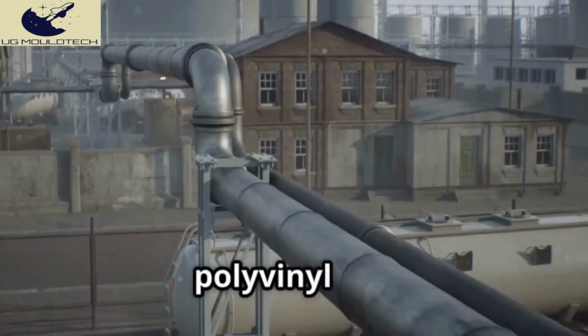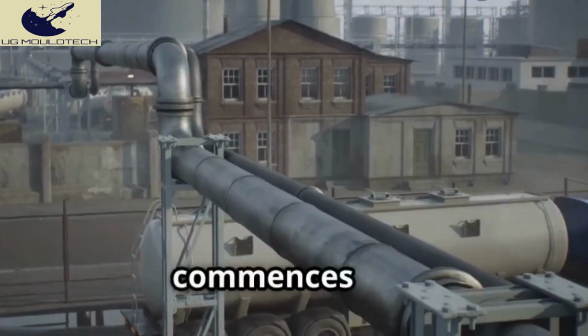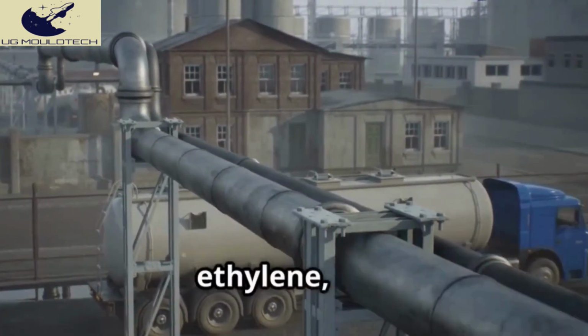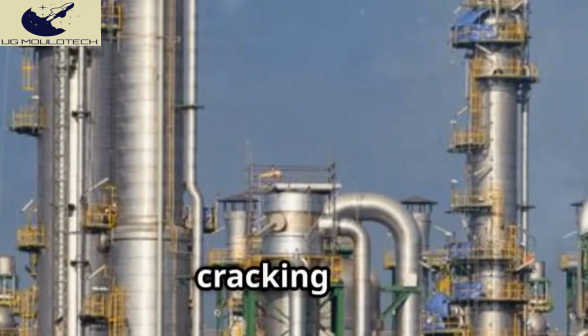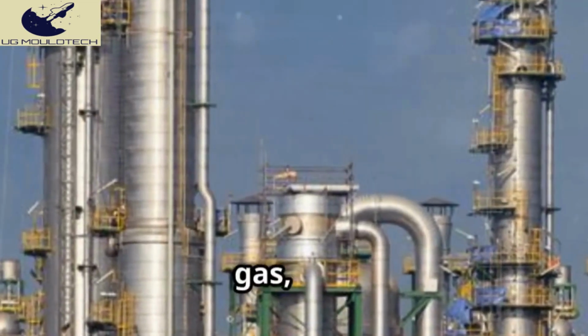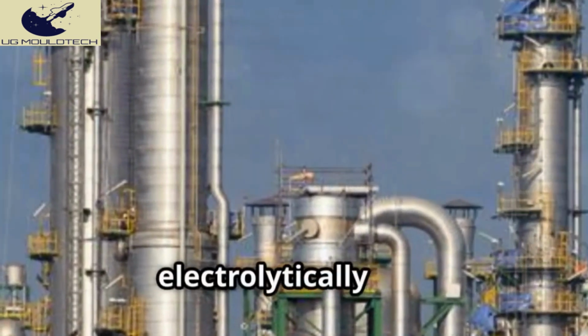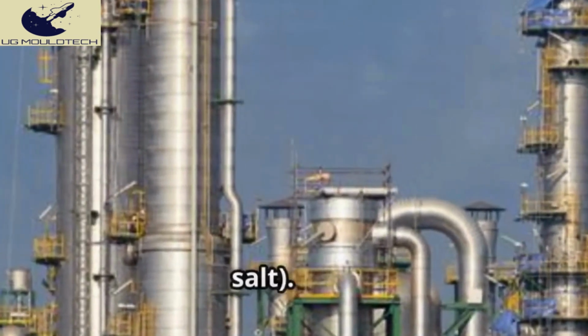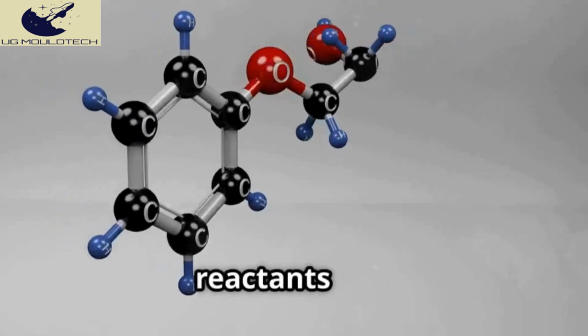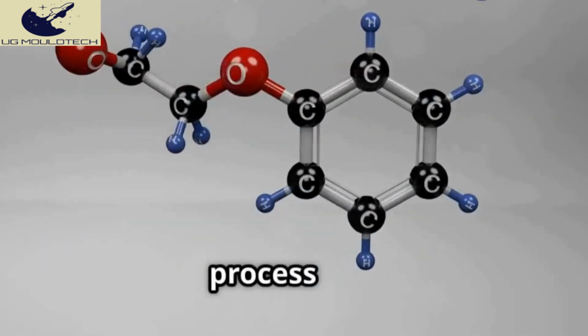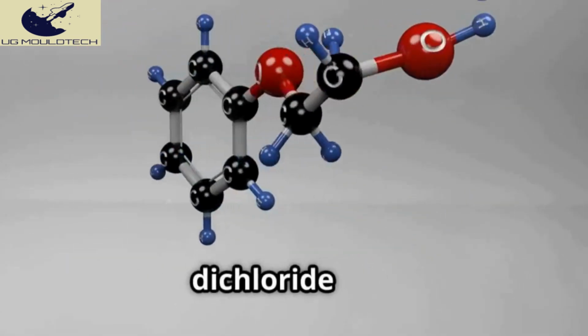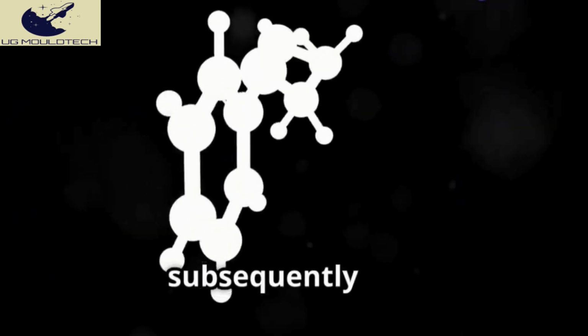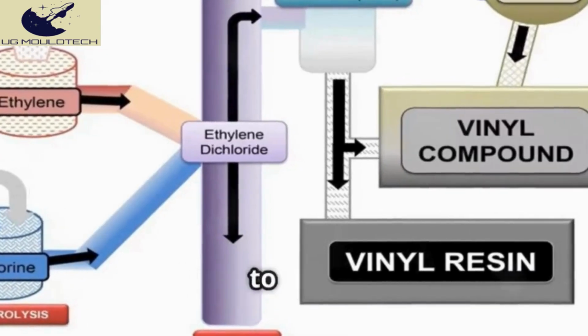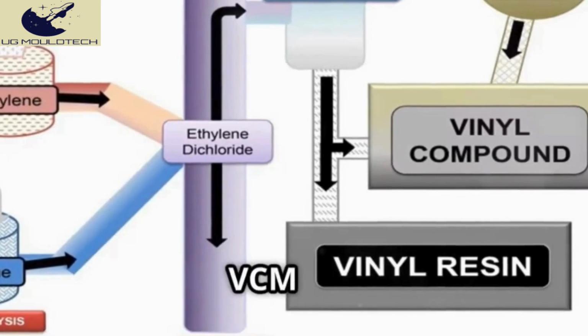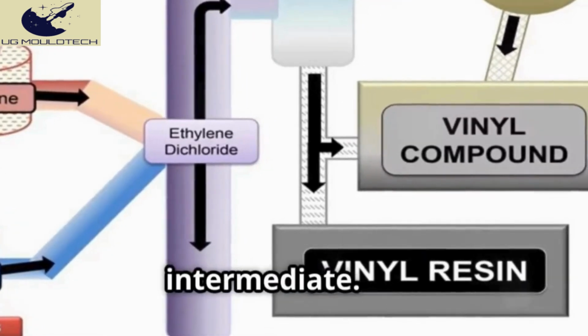The synthesis of polyvinyl chloride, PVC, commences with the procurement of ethylene, a hydrocarbon derived from the cracking of petroleum or natural gas, and chlorine, which is electrolytically extracted from sodium chloride salt. These reactants undergo a chlorination process to produce ethylene dichloride, EDC, which is subsequently subjected to thermal cracking to yield vinyl chloride monomer, VCM, a gaseous intermediate.